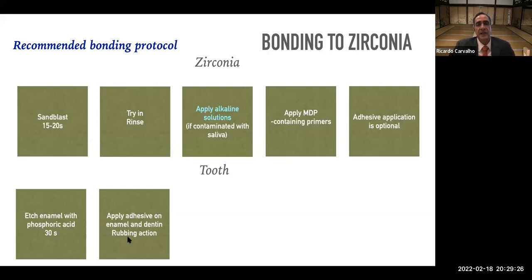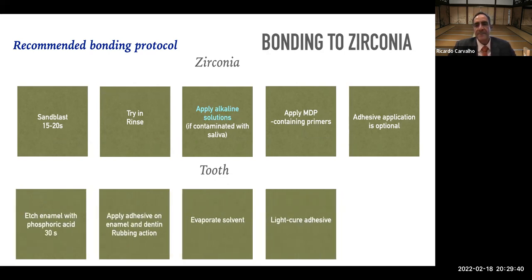But when you apply the adhesive on enamel and dentin, usually a rubbing action is recommended to, again, favor the evaporation of the solvent, which is always there, and it's important to be evaporated. Then you light cure the adhesive. This is important when we're dealing with crowns, even if you're dealing with a dual cure adhesive. I always recommend light curing to ensure that's the bond that you are ensuring.